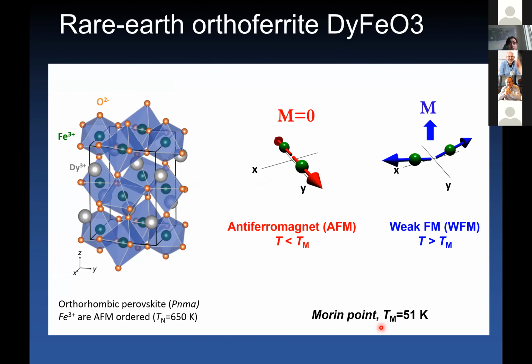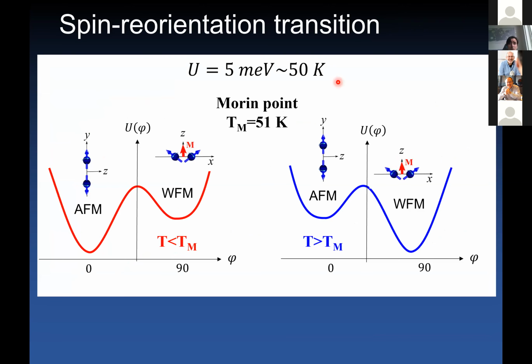And the material that we use for this study is the rare earth orthoferrite, dysprosium orthoferrite. So this is an orthorhombic system where magnetism comes from iron 3+. And in the low temperature phase, you have an antiferromagnetic collinear arrangement. This is below the Morin point located in the bulk at 51 Kelvin. And in the high temperature phase, you have a weak ferromagnetic phase in which you have spin canting and a net magnetization. So this is called the Morin transition or spin reorientation transition. And it's a first order type of transition that occurs around 50 Kelvin, with an energy barrier of the order of a few millielectron volts.